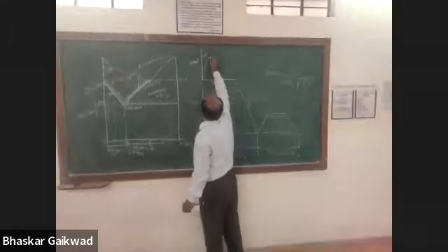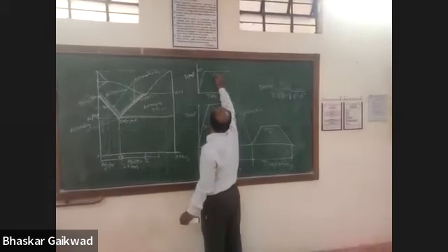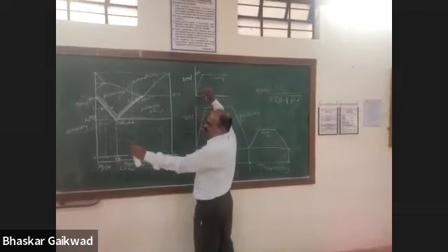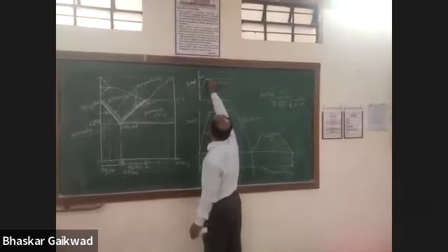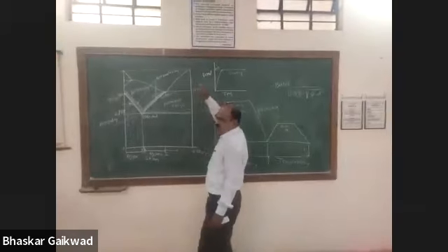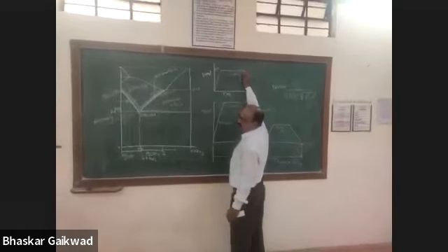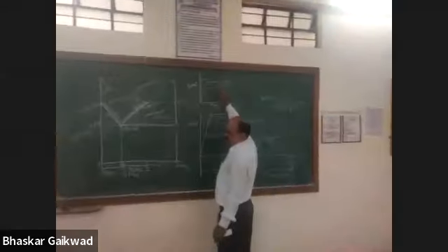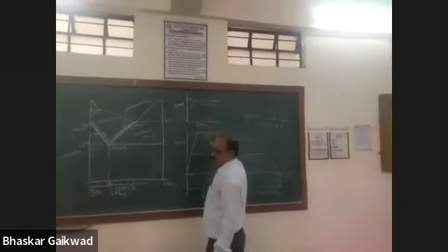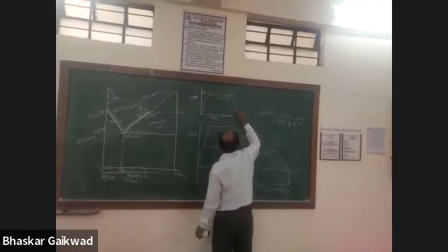After this, this is the soaking time, means constant temperature. Whatever temperature you kept in the furnace, you make it constant for 1 hour or more. This depends upon the cross section of the material. Normally it is 1 to 2 hours, and practically we can judge this timing.